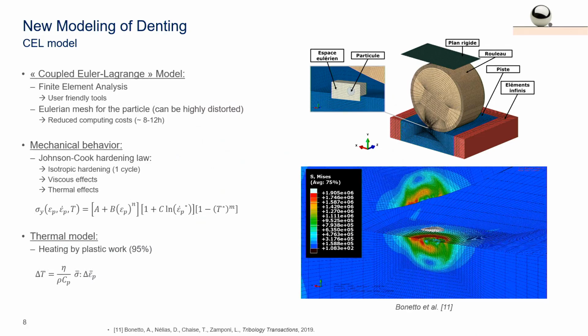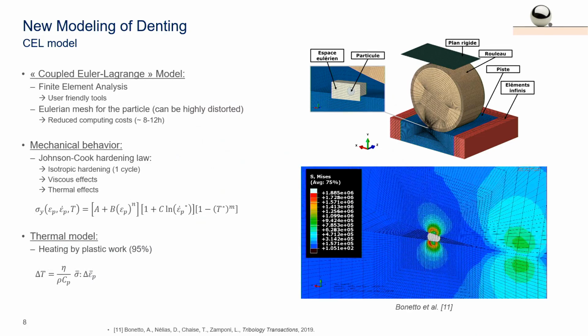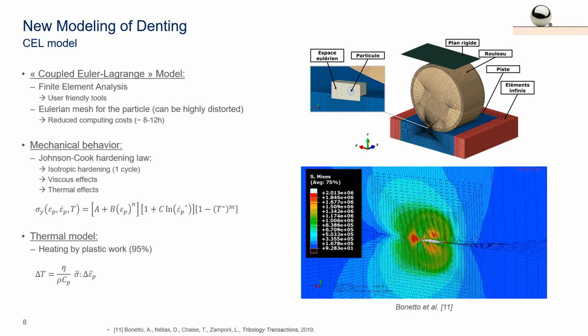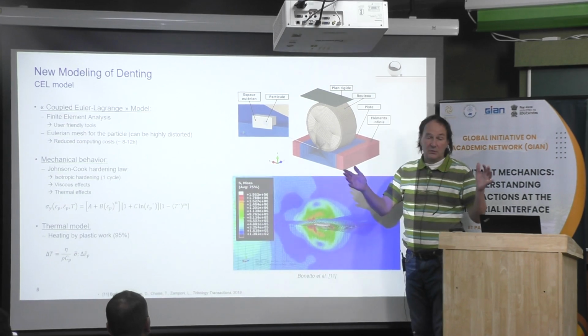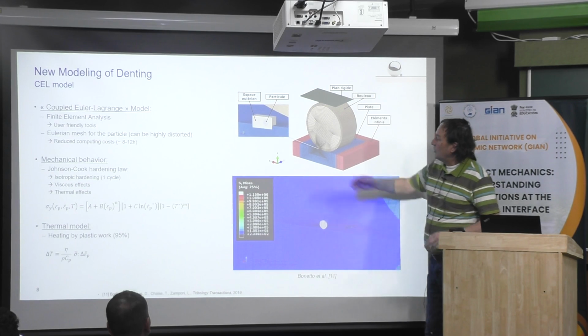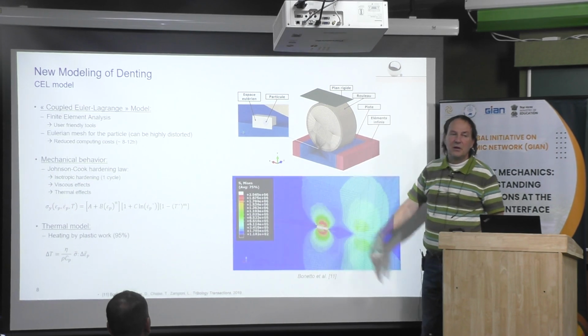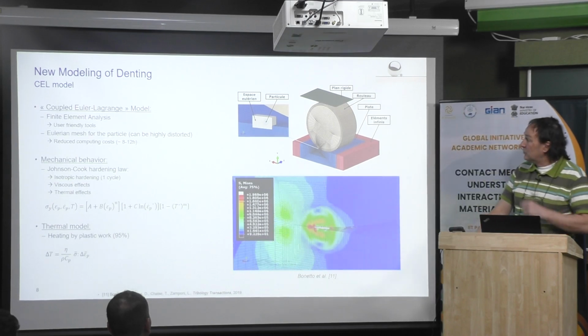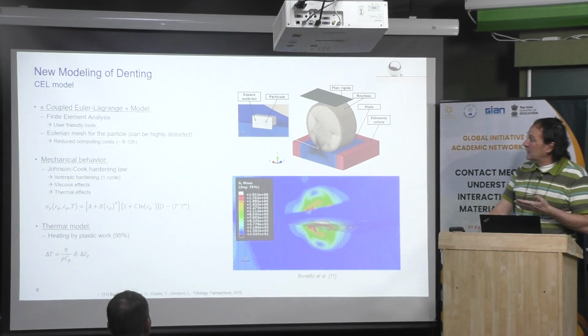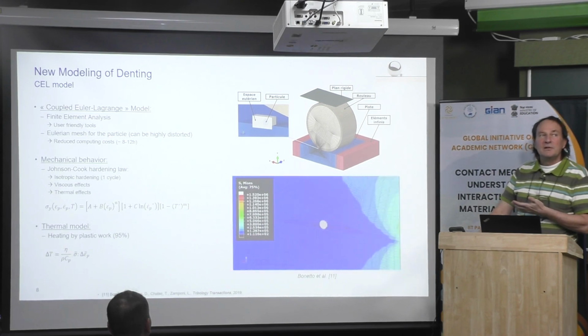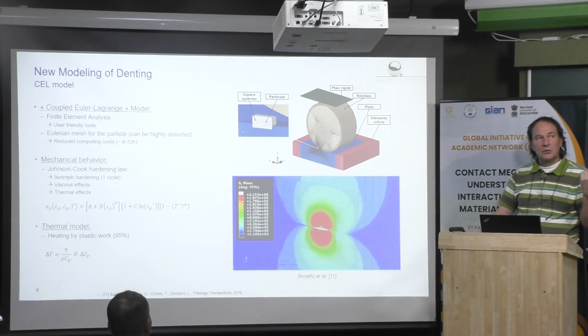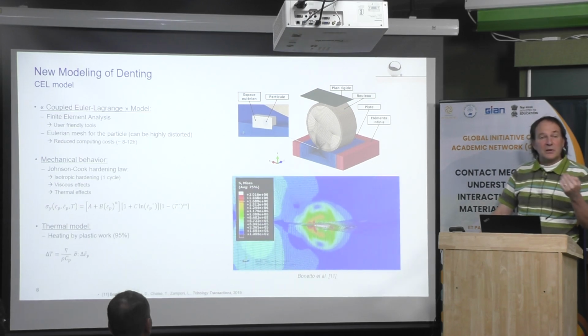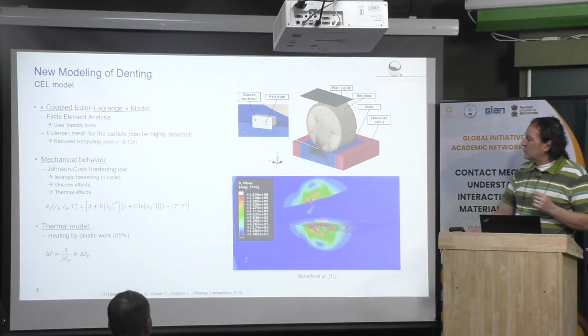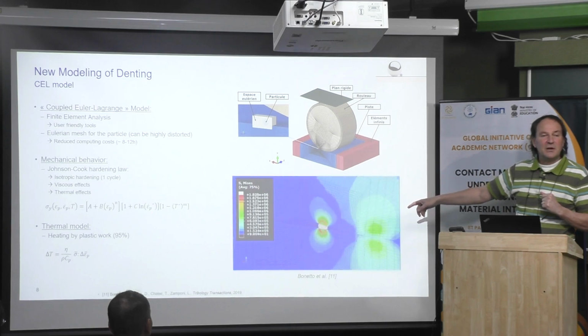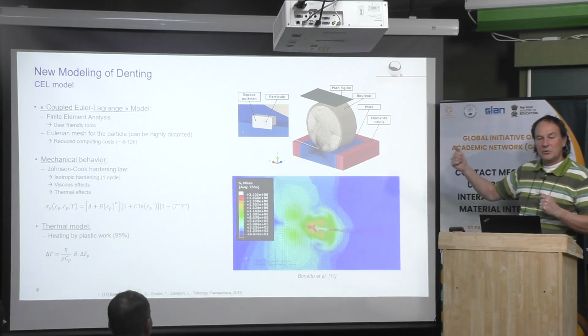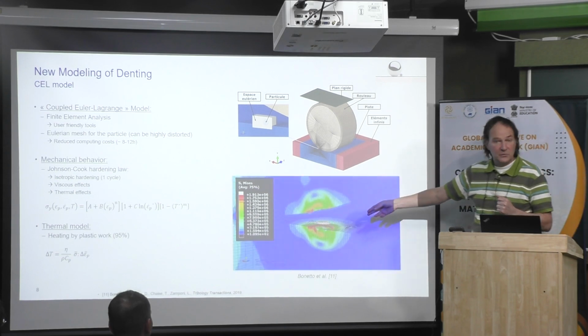Okay, this is what we did. You can see a simulation below. Here we have the Eulerian domain. The particle will deform like a fluid, and around it the two bodies are in a Lagrangian framework with a Lagrangian mesh. It's possible to do that with Abaqus. The main difficulty, maybe 10 years ago, when we did some work on cold spray and simulated it with this technique, was that it was not possible to estimate the heating of the particle. It was only isothermal. Now it's possible to transfer part of the deformation into heat, and then to predict the temperature of the particle.